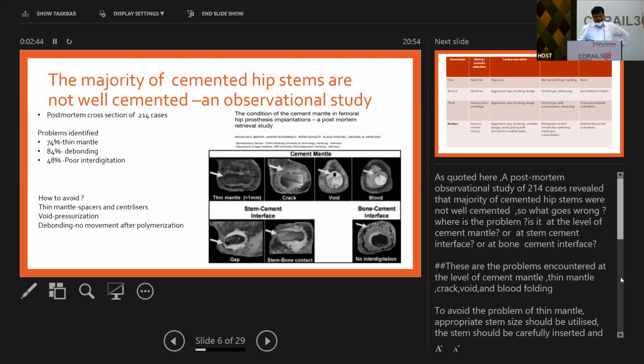The problems in the cement mantle are that you can have a thin mantle, or you can have a crack or a void and blood lamination inside the cement mantle. How to prevent a thin cement mantle? Use an appropriate stem, which reduces the thin mantle, and use a proper centralizer. How to avoid voids? Proper pressurization of the cement avoids voids.